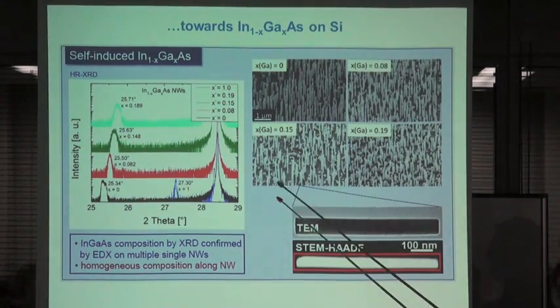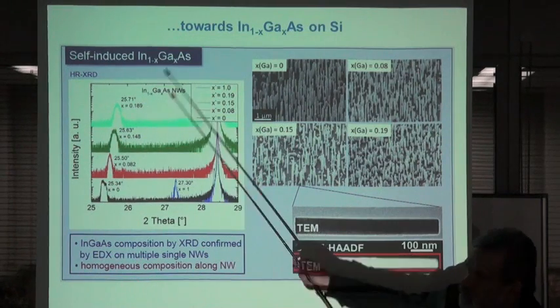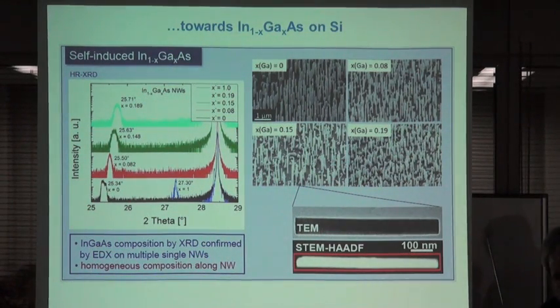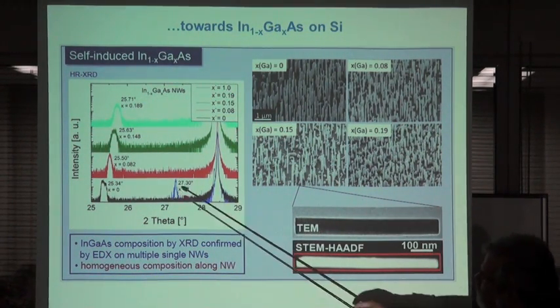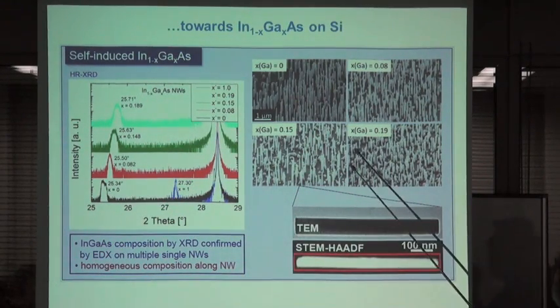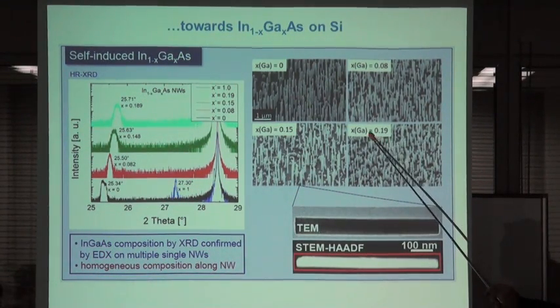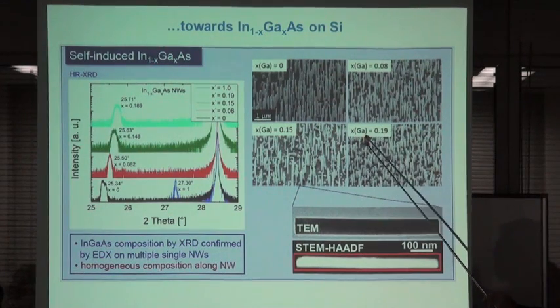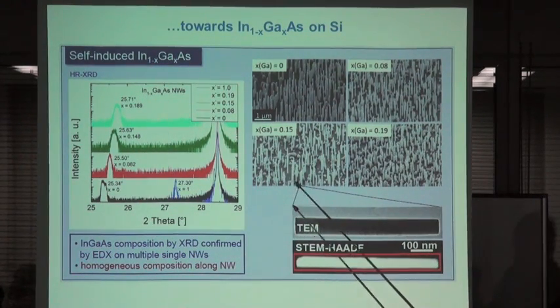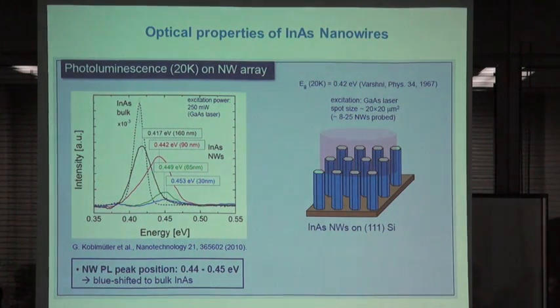At the moment we are testing if we can go to indium gallium arsenide, which is very important for axial heterostructures. This is just the first trial that we have here, 19% gallium in this case, because we start with indium arsenide here. And we do the same thing from the gallium arsenide side. And we have first successful wires also and first heterostructures along the wire. Now the optical properties of the indium arsenide nanowires: this is an ensemble measurement of maybe 8 to 25 nanowires.